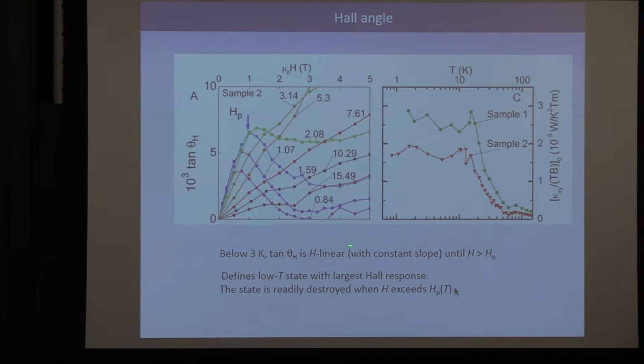By the time field ordering happens, remember I told you at 2 Tesla, there's some kind of magnetic ordering that occurs when the diffraction spots condense. Interestingly, it wipes out the thermal Hall effect. So this is a property intrinsic to the weak field entangled state that we identify with the spin liquid. Here's one other way to show it. We plot this slope, initial slope that's indicated by this ratio, versus temperature, and put it on log scale. And you see that it increases very rapidly below about 50 Kelvin, and then in this interesting phase, it saturates.